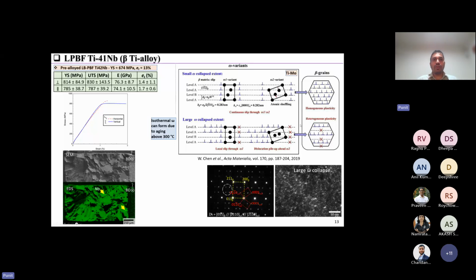We also verified this by printing small as-built coupons, and when we did tensile tests, we do see plasticity. We also tried solution treating the huge blocks that we had printed, and we see that when you do that, you lose significantly in strength. So that was something that we did not want to see.